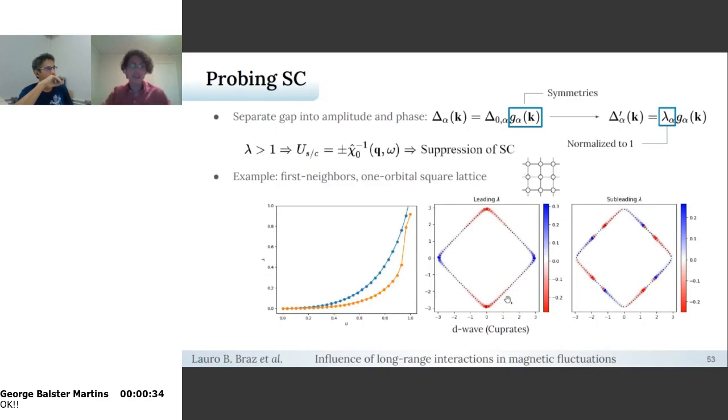And what I show in this other figure here is the gap function. I mean, this function containing all the symmetries, the momentum-dependent gap structure for the Fermi surface of the system in colors. So it takes positive values in certain regions and negative values in these other ones, meaning a symmetry, which is now D-wave superconductivity. And actually, that's really interesting because in the most famous systems present in superconductivity in a square lattice, the so-called cuprates, they do show D-wave superconductivity, and we can measure them. So that's the whole picture we can analyze using this theory.